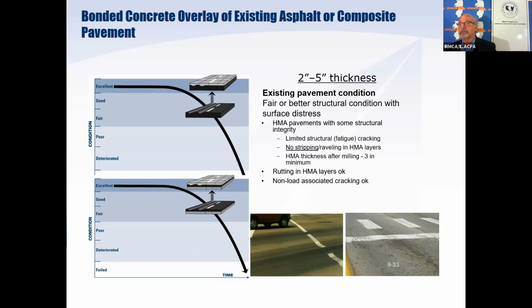Now, there are obviously a number of tricks of the trade that have to be employed in designing these. Joint spacing is very different. We typically use fibers in the concrete. We probably are going to mill the surface in order to get a good bond between the concrete and the asphalt. Because remember, if we don't bond to the existing asphalt pavement, that thin concrete overlay is going to fail under truck traffic.